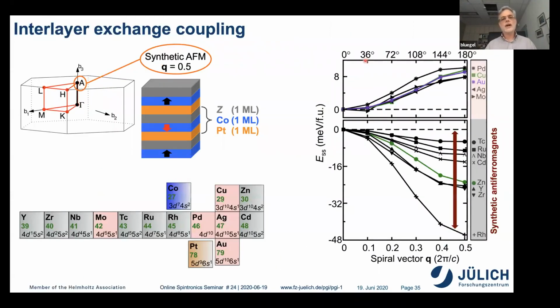We know which layers are coupling antiferromagnetically or ferromagnetically across the interface. So basically we see here these materials. This is the ferromagnetic state. This is the antiferromagnetic state. See, the antiferromagnetic state here has a lower energy. So all these gray elements here make the cobalt films couple antiferromagnetically, whereas these pinkish elements are coupling ferromagnetically.